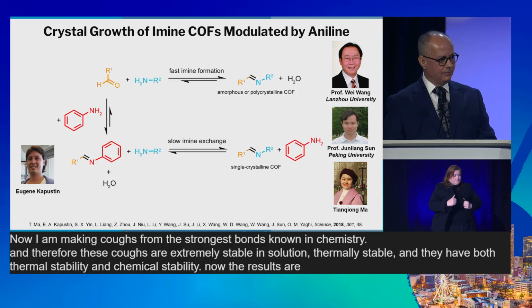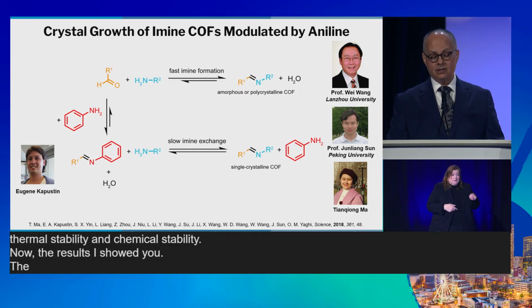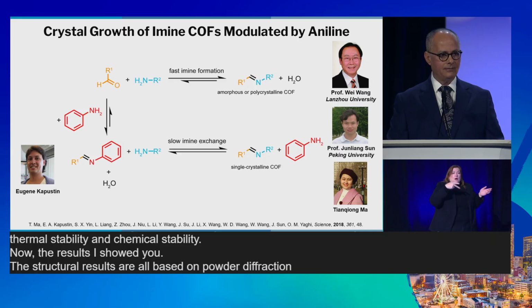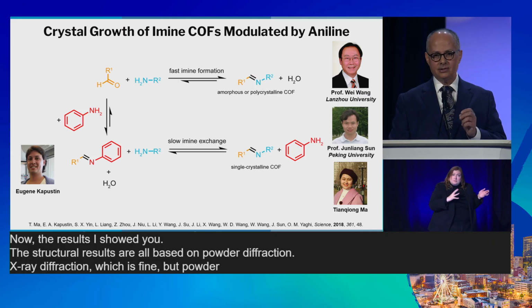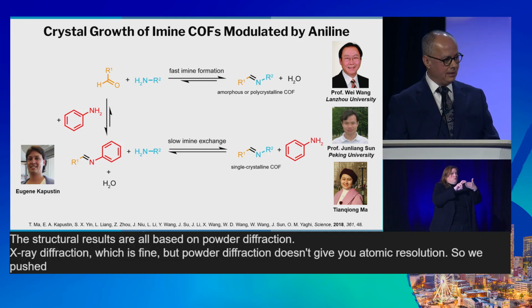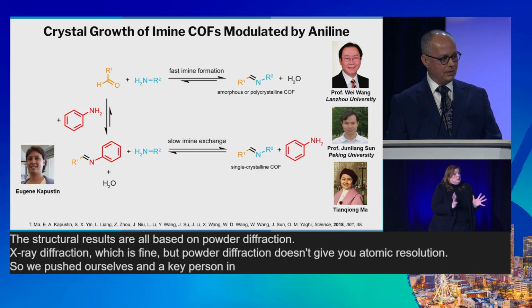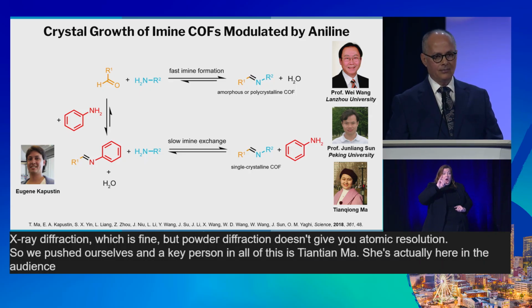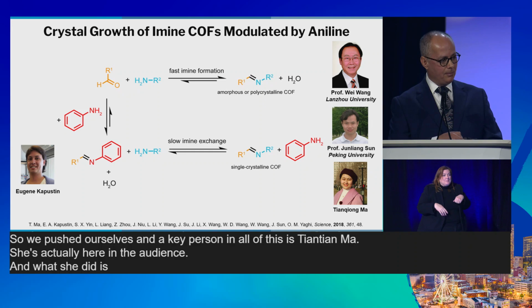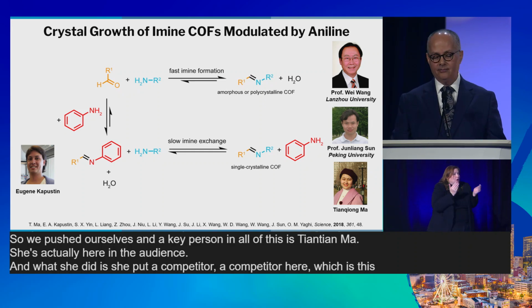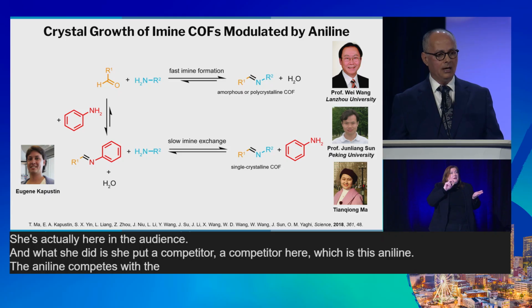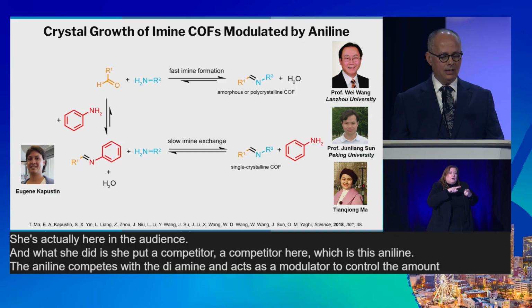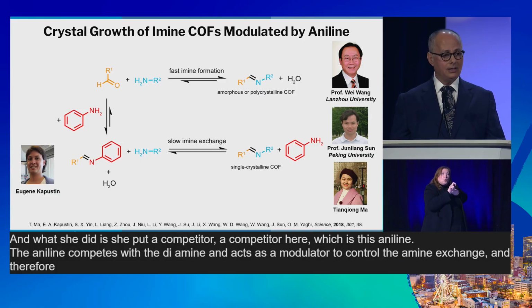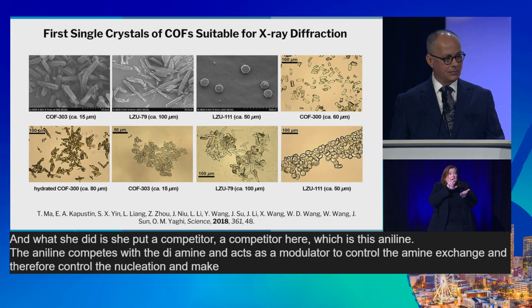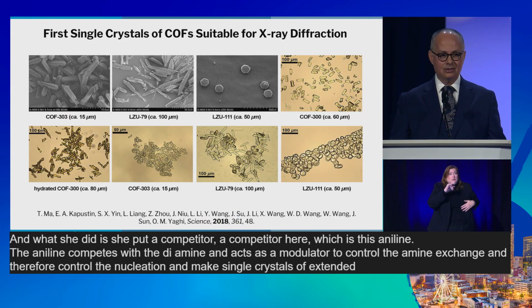Now, the structural results I showed you are all based on powder diffraction, X-ray diffraction, which is fine. But powder diffraction doesn't give you atomic resolution. So we pushed ourselves, and a key person in all of this is Tianqiong Ma. She's actually here in the audience. And what she did is she put a competitor here, which is this aniline. The aniline competes with the diamine and acts as a modulator to control the imine exchange and therefore control the nucleation and make single crystals of extended organic structures.